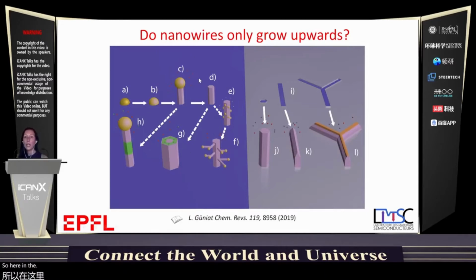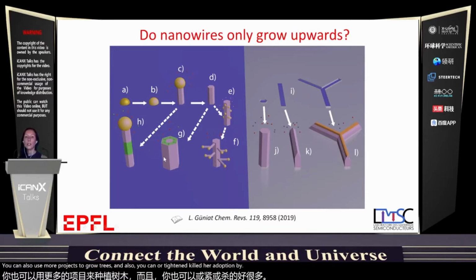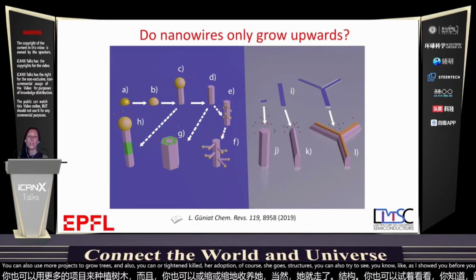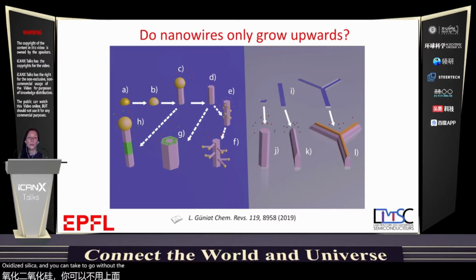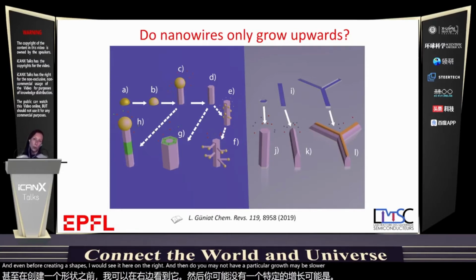So here on the left, you have the typical growth in which you have the metal droplet that drives the vertical growth. You can also use more droplets to grow trees. And also you can try to kill the droplet and make core shell structures. You can also try, as I showed you before, to make holes in the oxidized silicon, and you can try to grow without the droplet by just growing like you would grow a thin film in this localized area. If you have a hole, you would have a vertical wire going up. But you can try to just make this hole long, and even in more creative shapes, as you see here on the right. And then you may not have vertical growth, or it may be slower, and you may grow horizontally in certain directions. And that's what you see here in this scheme.